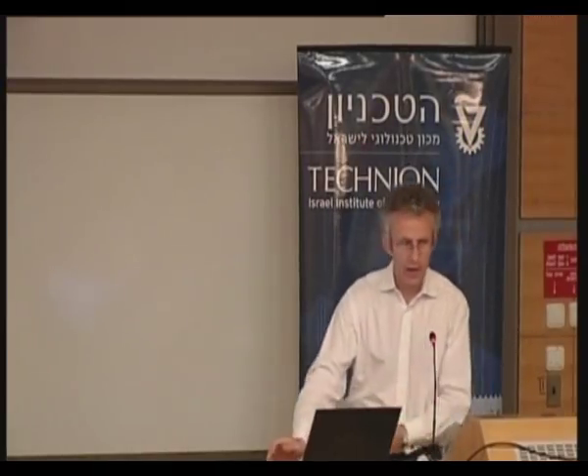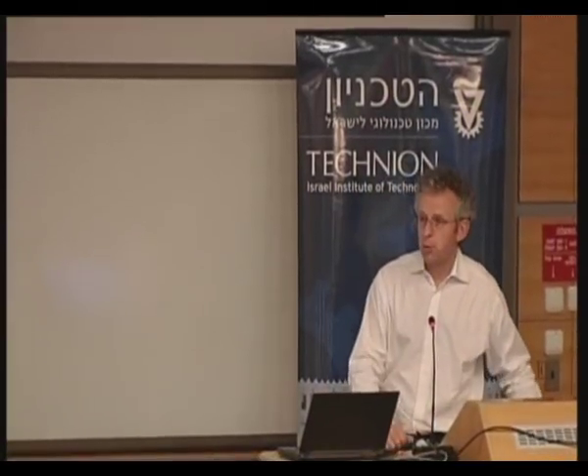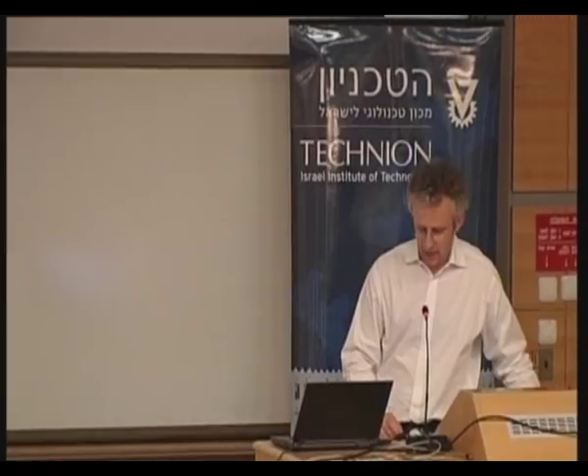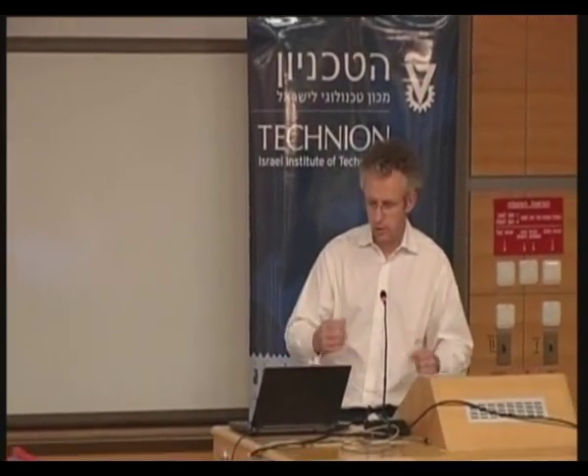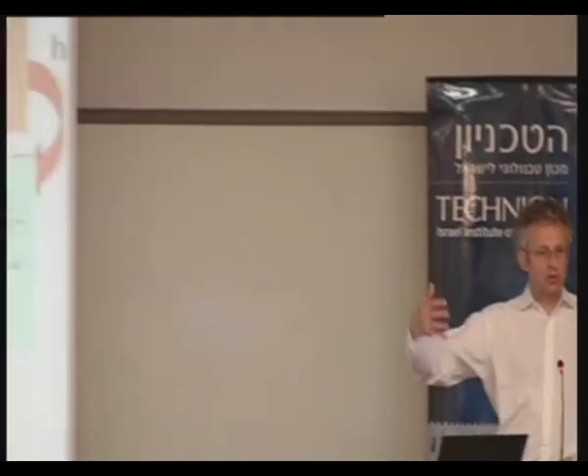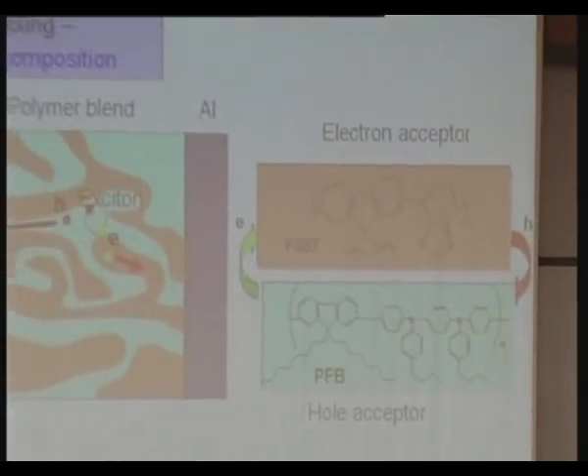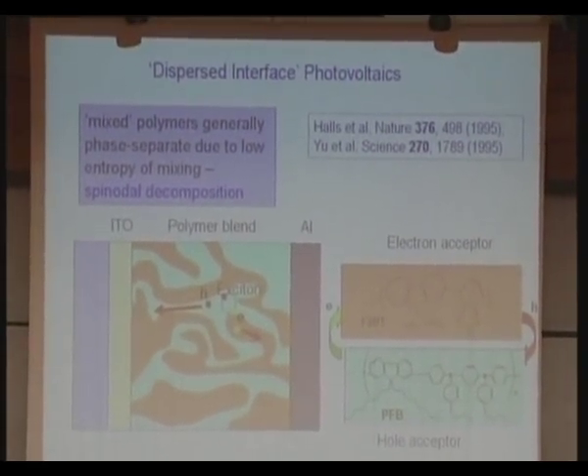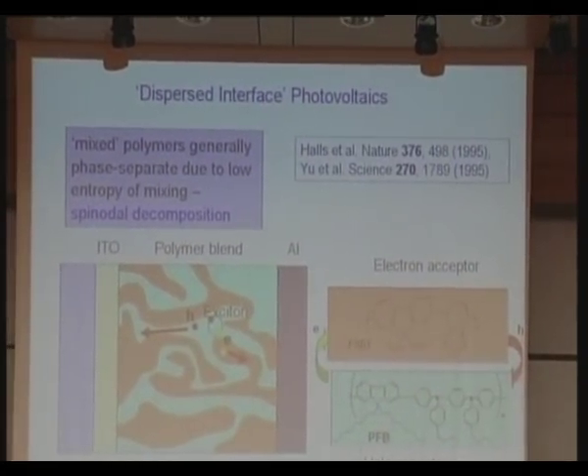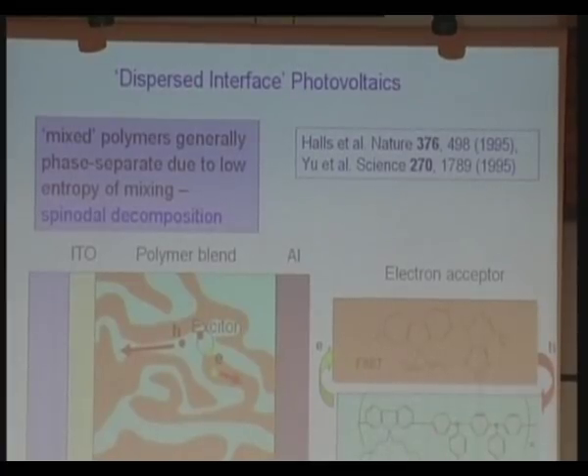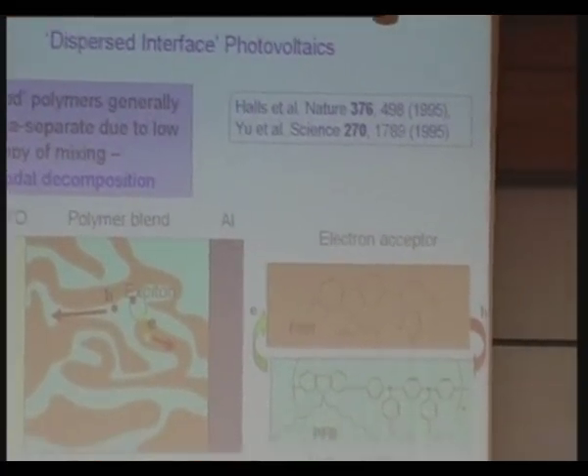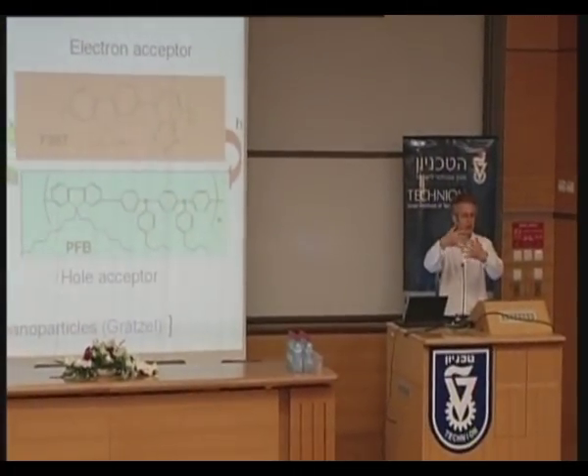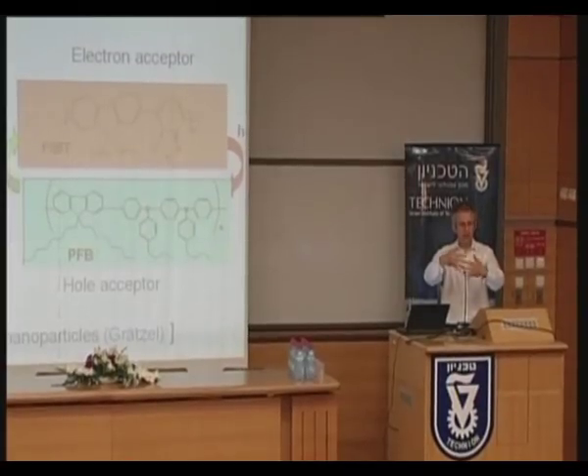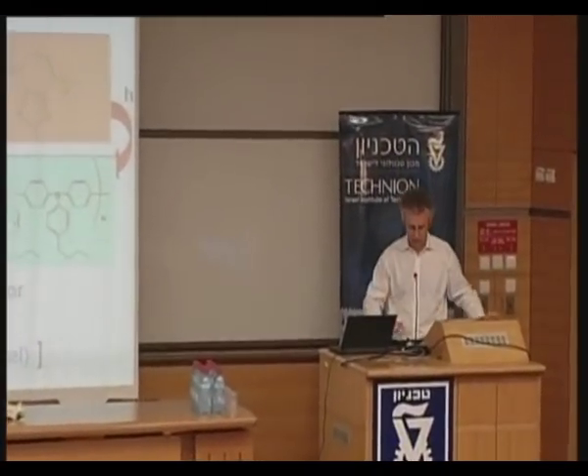And of course, nature has found very elaborate structures to tackle that problem in photosynthesis, with these spectacular light harvesting antennae molecular systems that funnel excitons down to the reaction center. A much cruder approach, which has been sorted out in many ways in the field, is to arrange that we have a distributed area heterojunction within an absorbing film. So the ideal structure would be a sort of interfingered organization where we have fingers that are no more than the dimension of the exciton diffusion range, so that it doesn't matter where light's absorbed, it will create an excitation which finds the heterojunction, charge separates, and then we can pull the charges back to the collection electrodes to make the photocell.